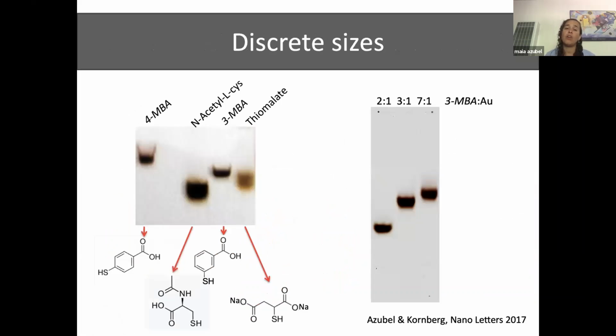So now to the question of which thiol. And I tried quite a lot of them. Again, doing the same trick, I was able to get this homogeneous product and a single band. And I also learned that if I change the ratio of the thiol to the gold at the moment of the synthesis, I will get products of different size. Why is this important? Well, I always say that size is for electron microscopy what color is for light microscopy. If we have different sizes, we can label different things simultaneously. And that's very important because, as I said, we were targeting all of these products to label protein and put it in the microscope.